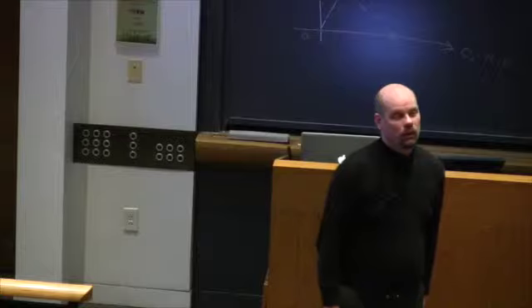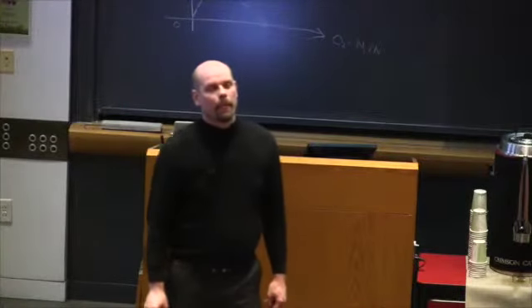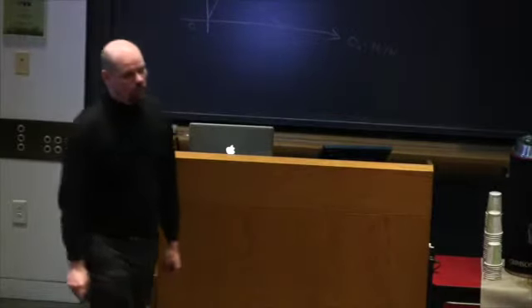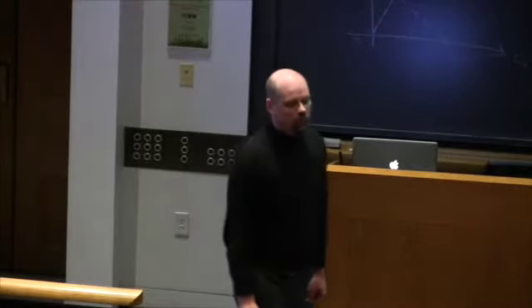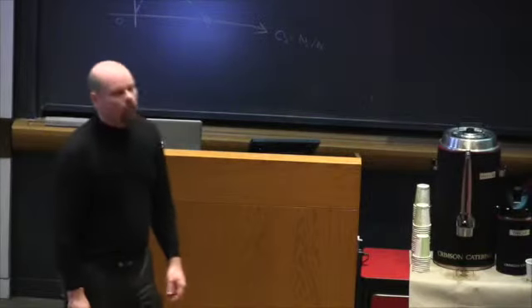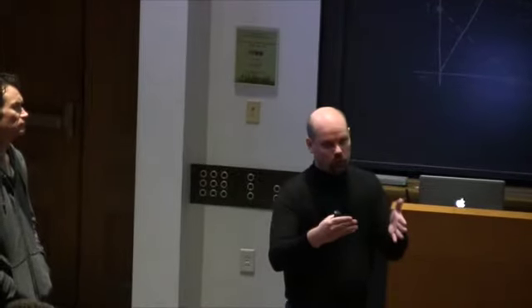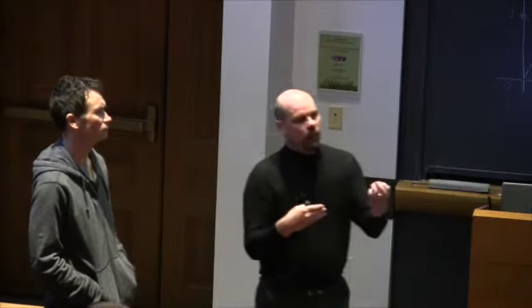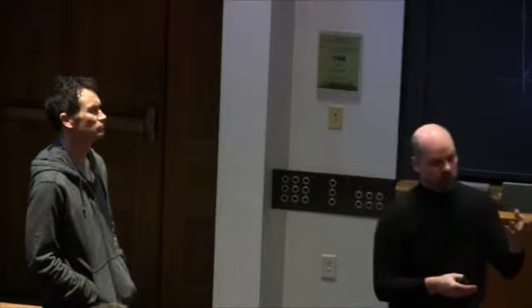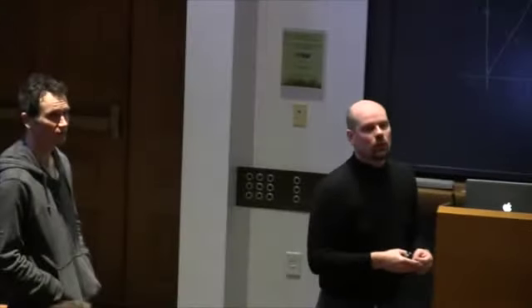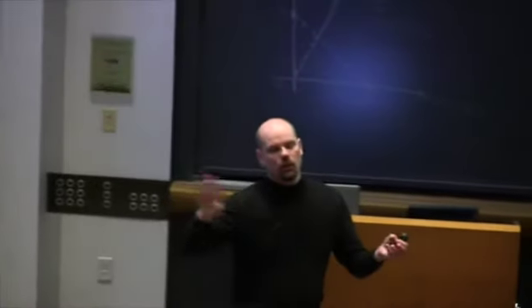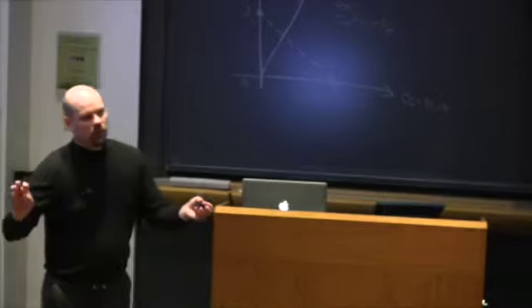So do you have some explanation for why things look so different in the (0, π) direction and in the (π, π) direction, in the Fermi surface behavior or something? If it's being damped by electron excitations, can you explain that? So the obvious way to go is to argue in terms of the Fermi surface, which I think is actually what has been done. But that relies on the interpretation of these excitations as purely charged. And that works, you say? In overdoped, yes, in overdoped this works. But then the question would be, okay, I have the uncorrelated quasi-particle, and in the overdoped system I'm very happy with just bands. How do I connect to the antiferromagnet at zero doping?